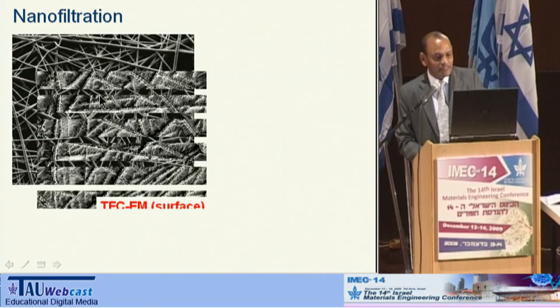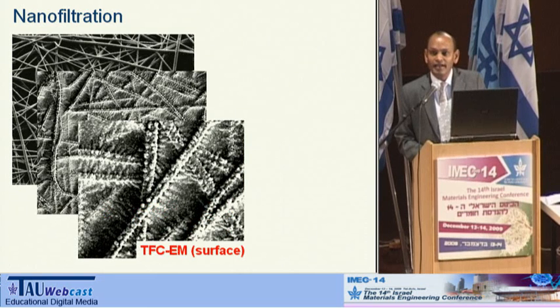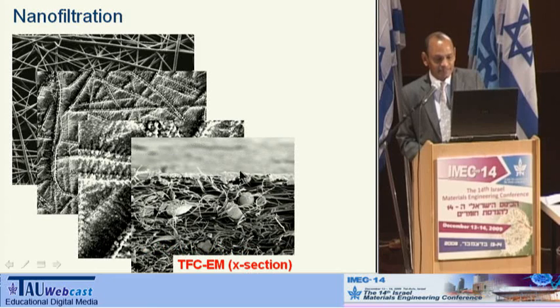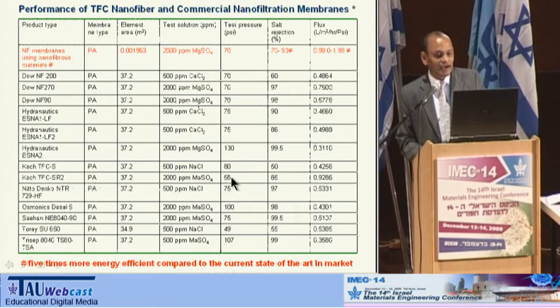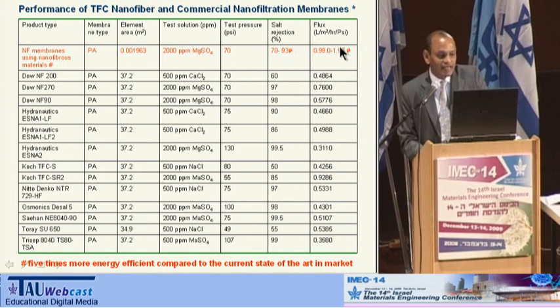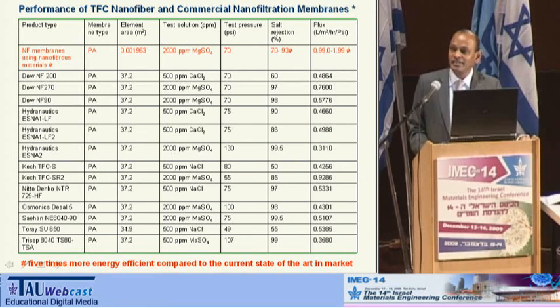And the other one, you could further use interfacial polymerization on these fiber structures. You can control the surface, and you essentially make nanofiltration structures. Here is the nanofiltration membrane of a polyamide material, and that is magnesium sulfate, the test pressure, the rejection level, and the flux. And these are all commercially available systems. And if you notice, it's five times more energy efficient compared to other systems.